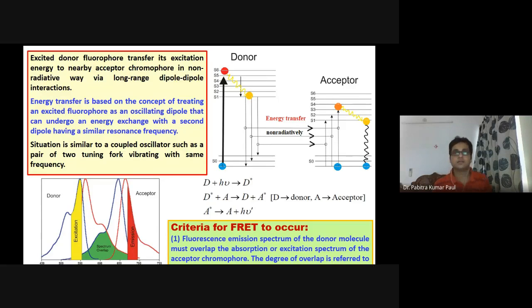So what are the main criteria or conditions for this FRET to happen? You can see this picture here. This is the absorption and emission spectra. This blue one and the yellow one are the absorption and emission spectra of the donor molecule, and this red one is the absorption and emission spectra of the acceptor molecule. So the main condition is that there should be sufficient spectral overlap between the absorption spectra of the acceptor and the emission spectra of the donor. The green shaded region, you see, is the spectral overlap.